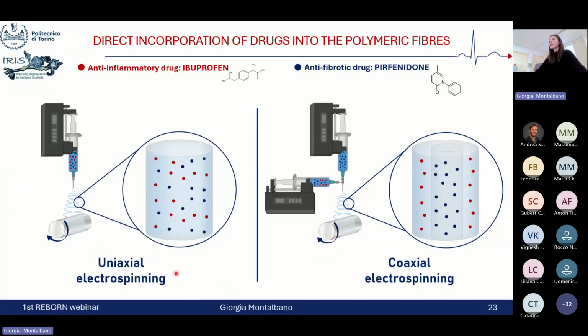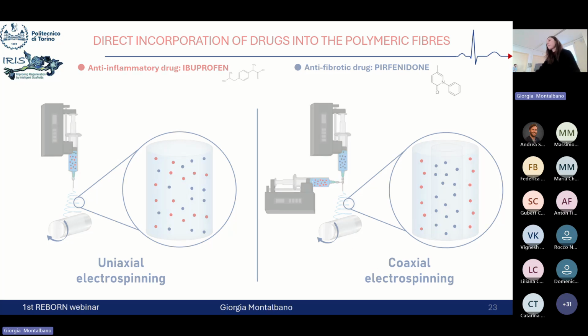So in parallel to this on-demand release of the drug, we also explored other strategies. And so basically the direct incorporation of the drugs into the polymeric fibers, exploiting the direct mixing with the polymeric formulation using both a uniaxial electrospinning setup and the coaxial electrospinning setup, with an attempt to better modulate the release profile of the two different therapeutic agents.